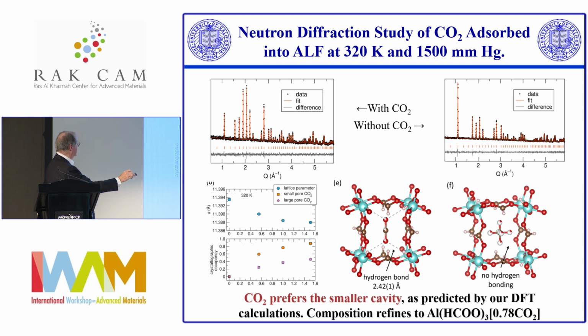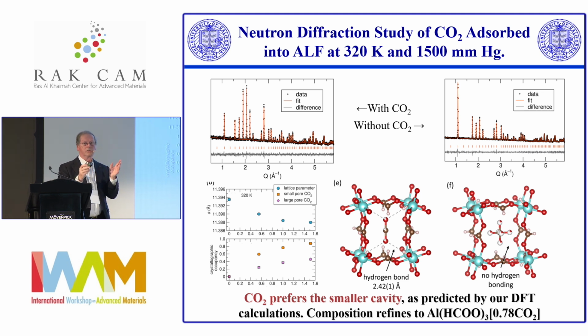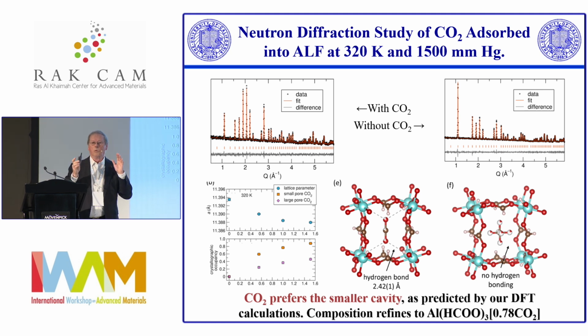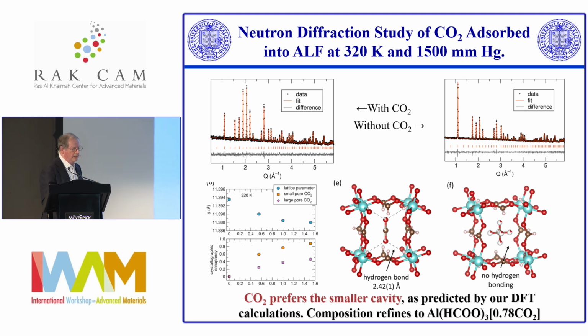These are the occupancy. So at sort of 1.5 bar, it's about 90% filled. In the larger cavity, the CO2 is disordered because there's no hydrogen bonding to lock it in place. So you can see that here. And that has a lower affinity for CO2, so the occupancy of that goes up to about 50%. So in the loaded material up to this partial pressure of CO2, nearly 80% of the cavities have got CO2 in. You can only get one CO2 molecule into each cavity. You can't do more than that. There's not enough space for it. So that's very nice characterization.